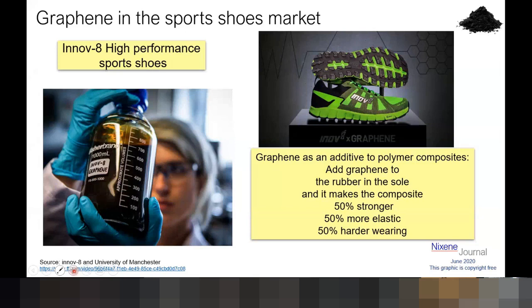They put graphene into the soles, and through this, they have now started to improve the performance of athletes through grip, because it's a softer grip, but it doesn't wear. Interestingly, they've had to reinforce the uppers with Kevlar because the uppers are wearing out before the soles are even starting to wear. As you can see here, by adding graphene, it's 50% stronger, 50% more elastic, and 50% more hard wearing. On the left there, you've got graphene oxide powder, which they put into a dispersion before it's polymerized. I always get that wrong, Adrian, with my teeth in. But yeah, they put it into a dispersion, which makes it easier to mix in with the rubber and then polymerize it. Yes, you're quite right, Mike.